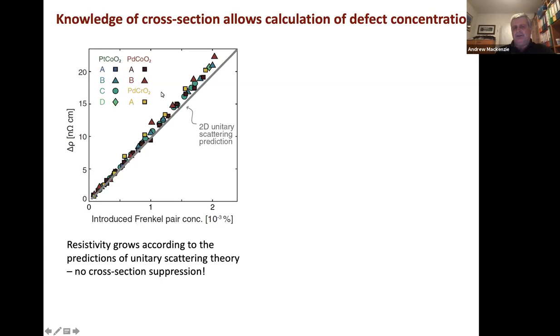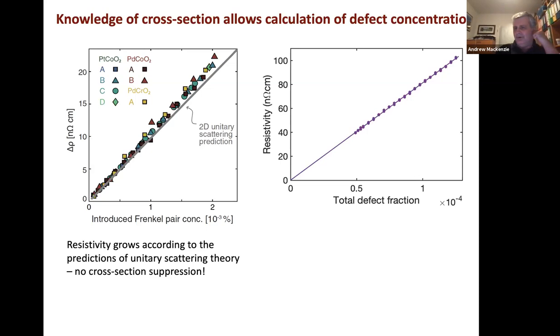And that then allows you to go one step further. You can take the data, say, from one crystal, and you can plot it, and you can see that the resistivity, this was delta rho above its as-grown state. So here's the as-grown state of that crystal. You extrapolate the line back and it extrapolates to zero or very close to it. So that line is then telling you what defect fraction would correspond to what resistivity, not delta resistivity, but starting resistivity as you measured it.